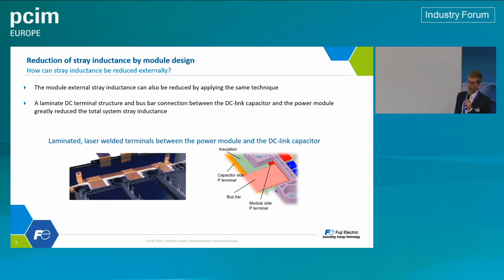And another interesting fact is that it is possible to reduce the stray inductance not only from the internal structure, but also from the external side. We can apply this technology also for the DC Link Capacitor, which you can see here in the bottom left, where we have the DC Link Capacitor in the backside, and with this laminated structure, with a schematic on the right-hand side with the red bus bar, you can tremendously improve the design.